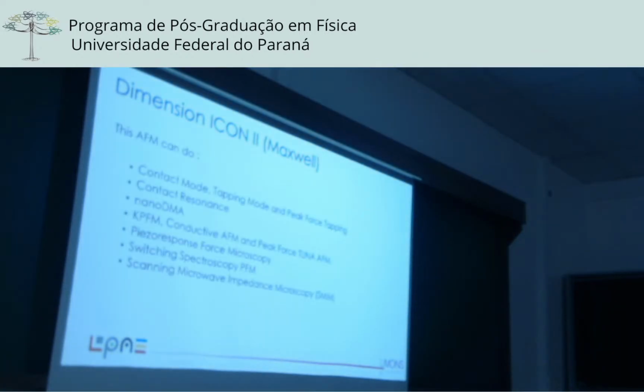So with Maxwell, it's possible to run all these modes to get the mechanical properties, to get the conductive AFM, to have the piezo response, and also a new mode, which is scanning microwave impedance microscopy. And with this, it's possible to measure the permittivity and the conductivity of the samples.